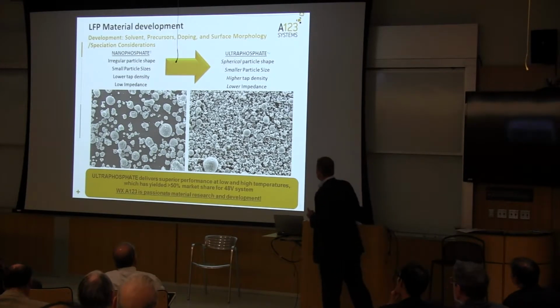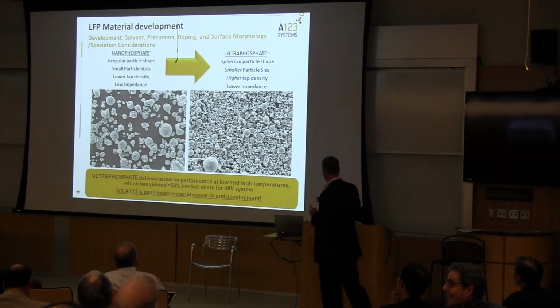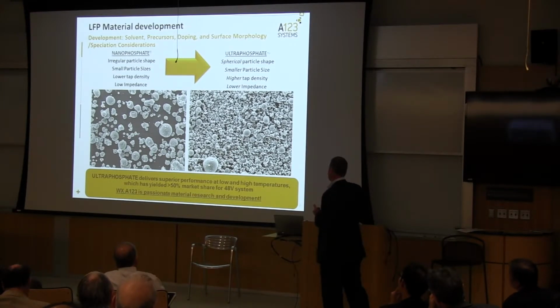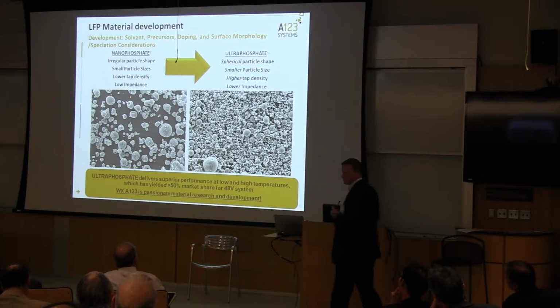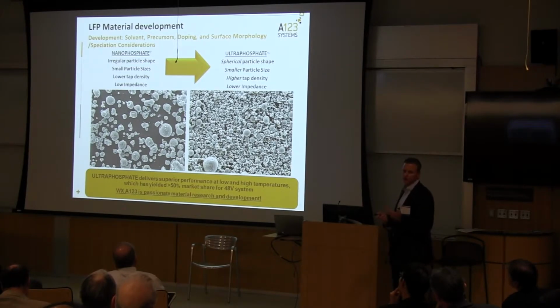Oh God, that's a great question. So, oops, let me go backwards. I could tell you it's probably on the order... So this guy right here, I would say, is probably about 8 microns. So the primary particle size varies between 60 and 80 nanometers, and our D50 typically is around 3 to 4 microns. Yeah, that would have been helpful to have a scale bar on this.